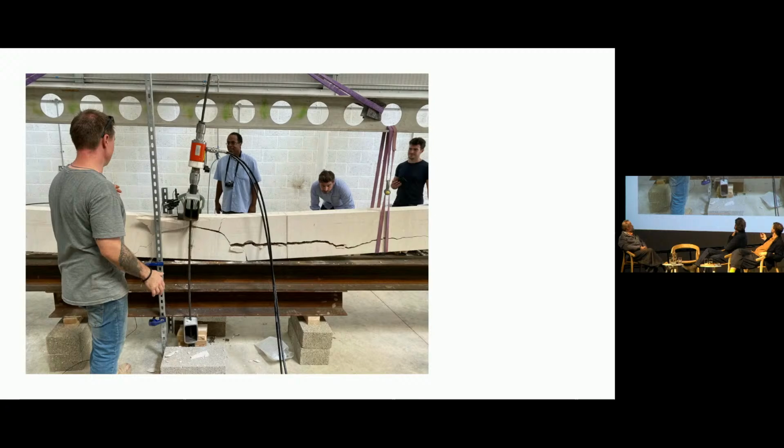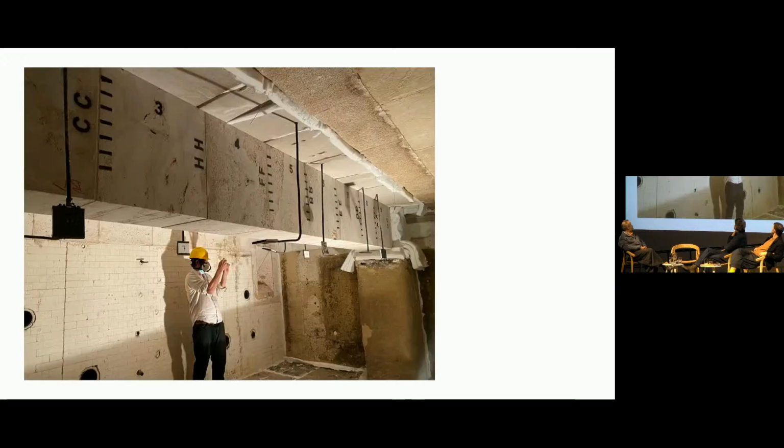So Sebastian from UCL and Pierre's partner Alex were testing beams to destruction, to see how strong they are. When we designed Clark Close, we were saying, oh well, limestone doesn't burn. Shortly afterwards, I started thinking, oh yeah, you burn limestone to make lime, don't you? So at 700 degrees, the building is going to turn into cement. So we thought maybe we'd better do some fire testing.